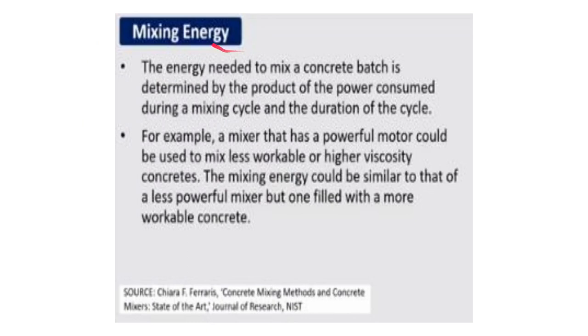So let us now go to the mixing energy. The energy needed to mix a concrete batch is determined by the product of the power consumed during a mixing cycle and the duration of the cycle. So the product of power and duration gives the energy. For example, a mixer that has a powerful motor can be used to mix less workable or high viscosity concretes, because it is more powerful. Whereas a less powerful mixer can be used for mixing more workable concrete, because less power is required.